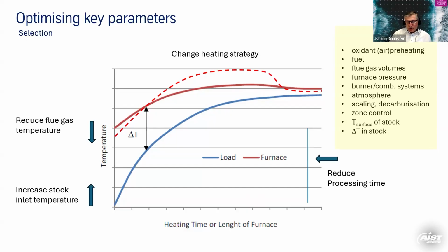But in any case, you have to look at air preheating. You have to look at the flue gas volumes. For example, when you have natural gas and you want to use another fuel like hydrogen or something else, or oxygen instead of air, you might have completely different flue gas volumes, which are lower than natural gas flue gas volumes. They completely change the heat transfer and also the pressure in the furnace, for example. So you can look at the burner systems. You have to look at the scaling and decarburization topic, and in the end, how do you achieve all that with different zones in the furnace which you can control? That means you have to split the combustion system into different zones, and also control those zones in the end.